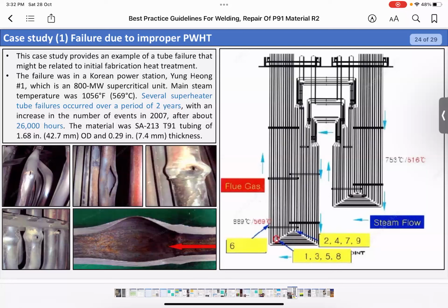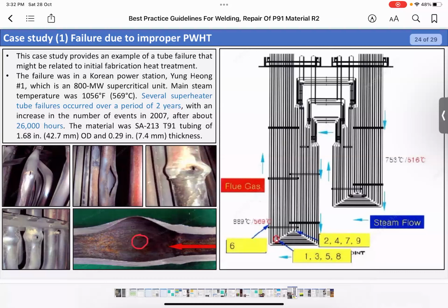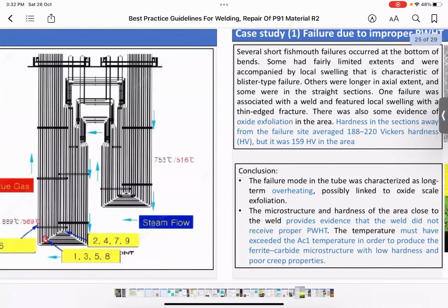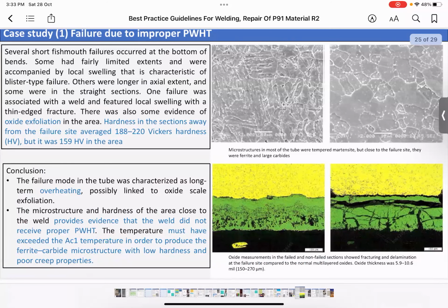So we see the fish mouth cracking in the tubes, and the hardness here was much lower than the hardness away from the weld. So this is a sign we had a soft grain, and this is evidence that the AC1 was exceeded during the weld. As I said, the hardness in the section away from the weld on the failure side averaged between 188 to 220 Vickers hardness, but it was around 159 in the area of failure.